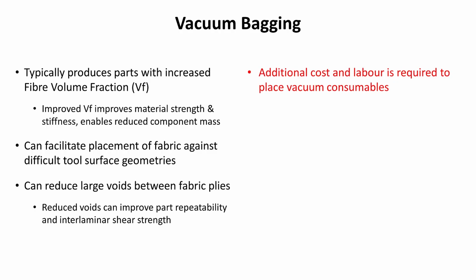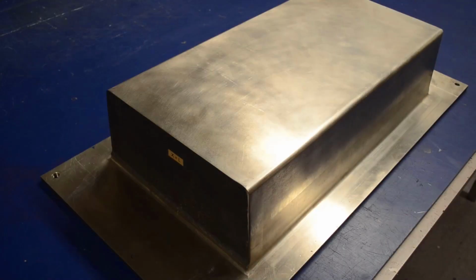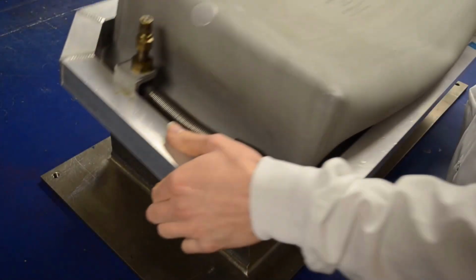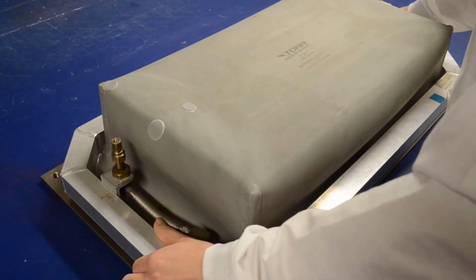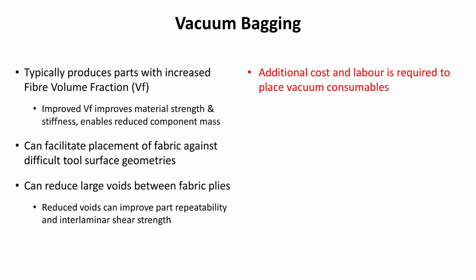Preparing the vacuum consumables and placing the bag for the large parts took about 30 minutes and required a vacuum pump. In a production environment, a reusable vacuum bag fabricated out of more durable rubber can reduce layup time and consumable cost. A limitation of vacuum bagging is that it benefits from a more stiff tool than open-air curing and requires a non-porous tool. Vacuum bagging produces forces on the tool which can deform it and hurt part tolerances if the tool is made out of very soft material.